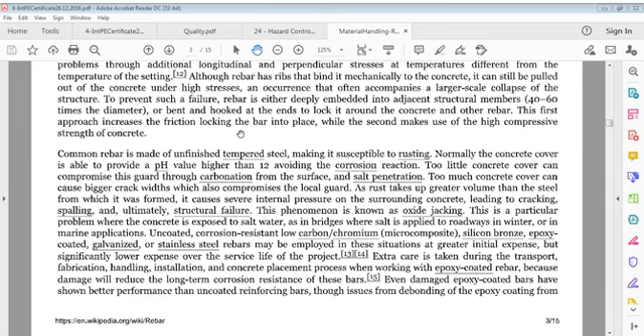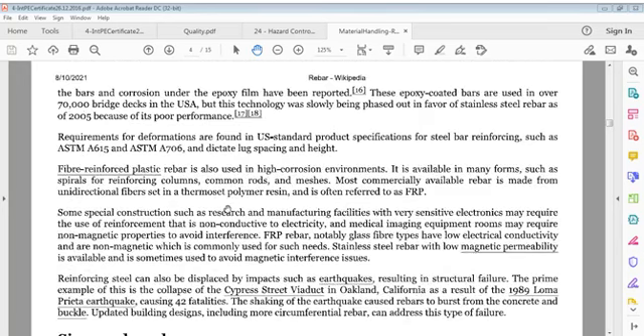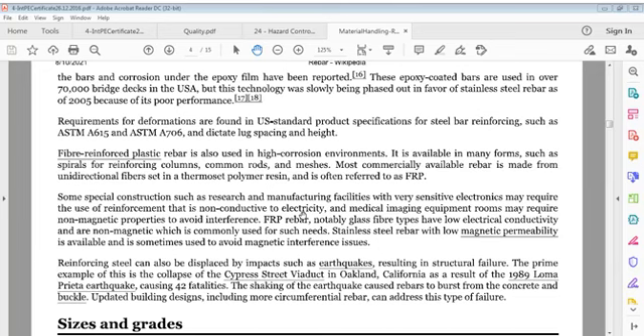Uncoated, corrosion resistant low carbon chromium, microcomposite, silicon bronze, epoxy coated, galvanized or stainless steel rebars may be employed in these situations at greater initial expense, but significantly lower expense over the service life of the project. Extra care is taken during transport, fabrication, handling, installation, and concrete placement when working with epoxy coated rebars because of the damage or reduced long-term corrosion resistance of these rebars. Even damaged epoxy coated bars have shown better performance than uncoated reinforcing bars, though issues from debonding of the epoxy coating from bars and corrosion under the epoxy film have been reported.